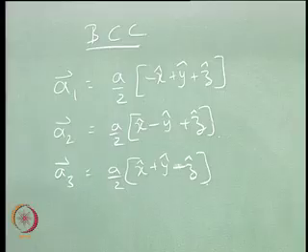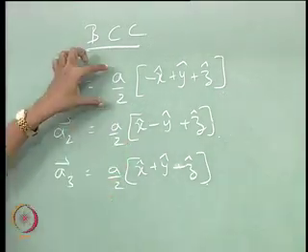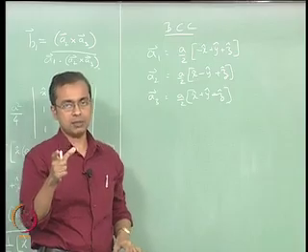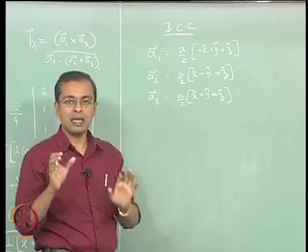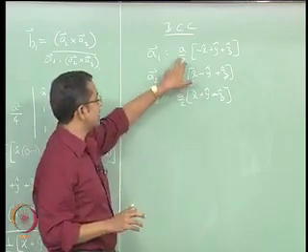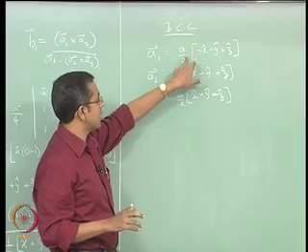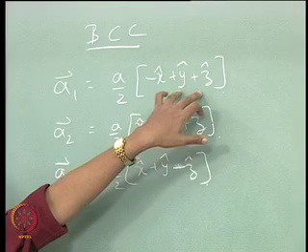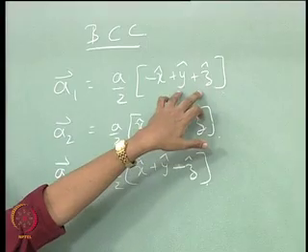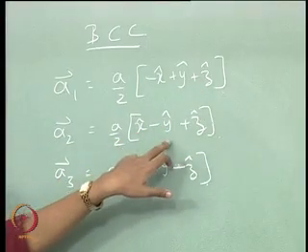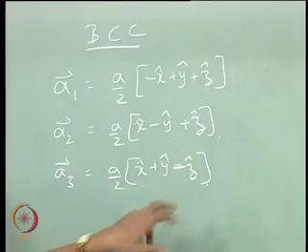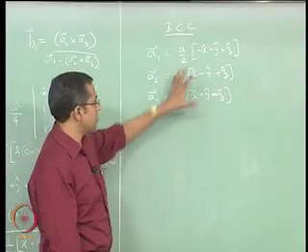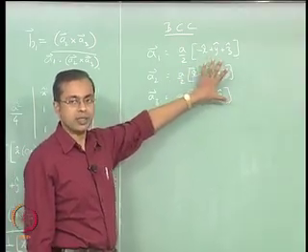As I mentioned, this is very clearly going from the origin to the 3 body centers. This is a by 2, which gives you the dimension that you are only travelling half the distance of that valid lattice length. So the lattice vector is a, and you are travelling a by 2, and then you are travelling halfway between in the y and z directions, and down the x direction half the length. That will get you to a body centered location. Similarly, this will get you to a body centered location, and this one too. So these are 3 vectors that go from the origin to the 3 body centers, fine. Therefore this is a representation of the body centered cubic structure.